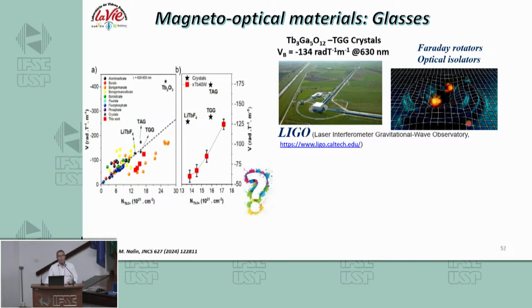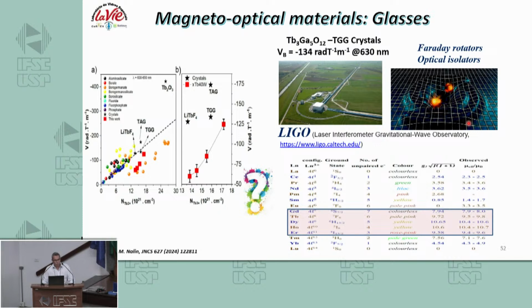If you enter the site of LIGO, because it's an open lab, you can see that one problem is the crystals have some problems with temperature. They increase in temperature. When you work with magnetic things, temperature is not good because the efficiency will decrease. So if you can work with a glass that is an insulator, it could be good. But we need to achieve the same, or at least close, property in the Verdet constant. This is why we are using glass to study this. The best one in this case is terbium, because of the absorption. Dysprosium and holmium are even better than terbium, but they absorb a lot in the visible. So this is why terbium is the best one.